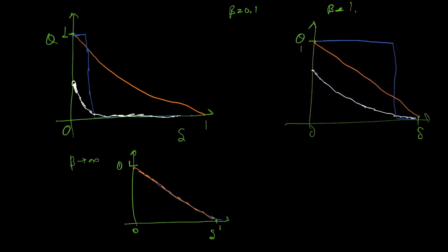It would be linear, but because it's a small thin film, it cannot equilibrate with the boundary temperature completely, and there would be some temperature drop immediately with the isothermal boundary conditions we have applied. So this is for a case where it is a thin film, let's say 100 nanometer or so, for all these figures.